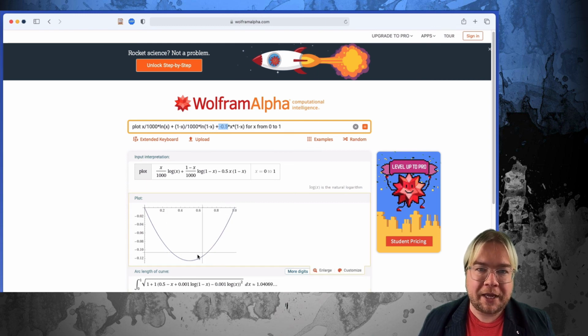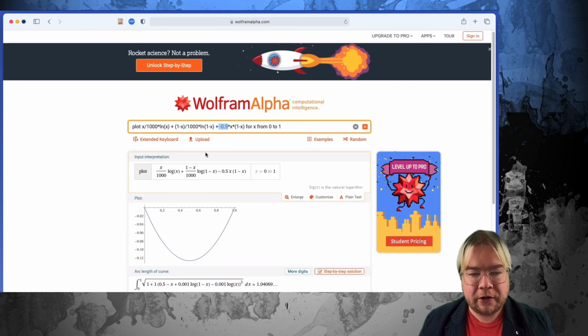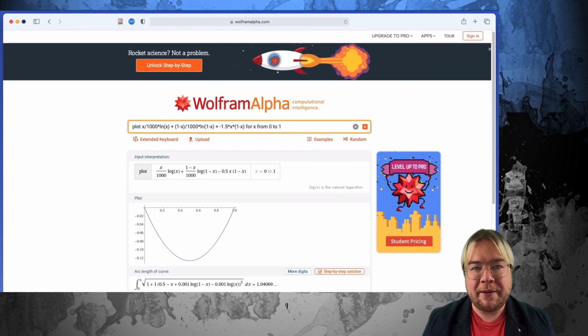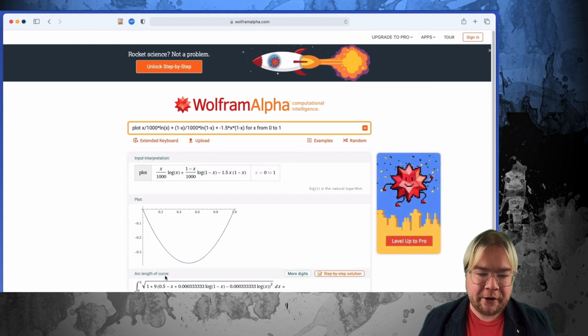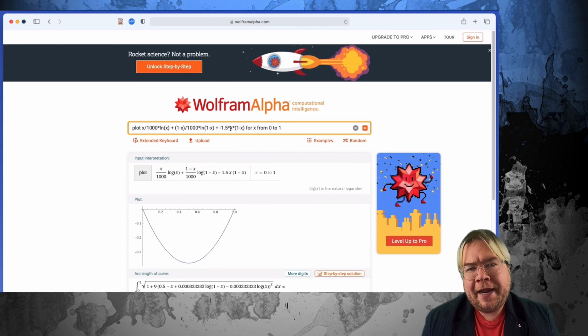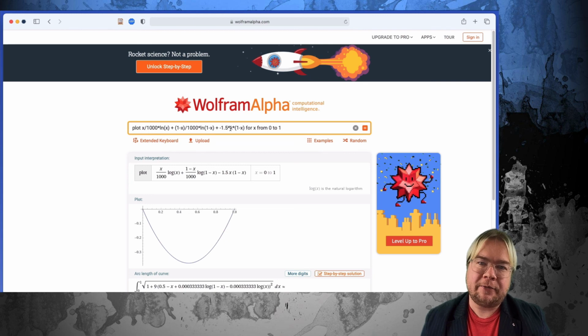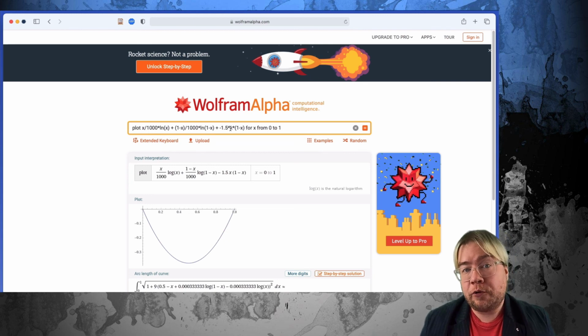And I'll talk about the implications of the shape of this curve in the next video again. So if I made this even more negative, then you can imagine that I'm going to take a negative value of the function and make it even more negative. And that will happen here. You see that now I'm even more negative than what I was at before. So a negative chi parameter means that interactions between opposite species, between A and B, are more favorable than interactions between species of the same type, so A or B.